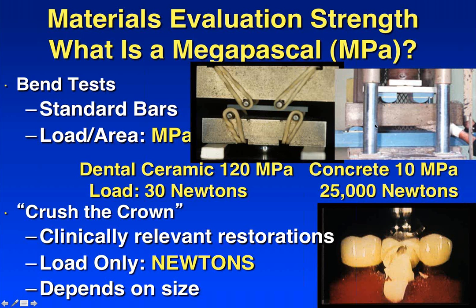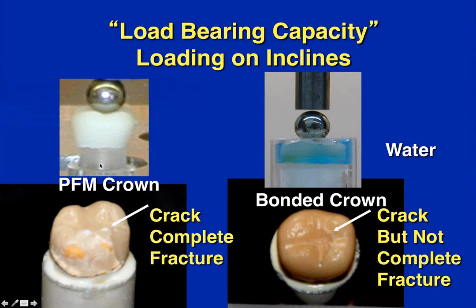Concrete is only 10 megapascals. But if you look at the load-bearing capacity of this thickness of concrete, it's 25,000, whereas that of our dental ceramic here is only 30. So load-bearing capacity, I think, is what we really want to be focusing on, and not strength. Everybody tends to focus on strength. We do a lot of load-bearing capacity tests. This happens to be one where we're looking at PFM and bonded crowns. We usually do them in water because obviously they're going to be in the mouth. You can also thermal cycle them, so they go from 5 degrees C to 55 degrees C, and get an idea of how these materials might survive in the mouth when they're being used the same way you're going to use them in the mouth.